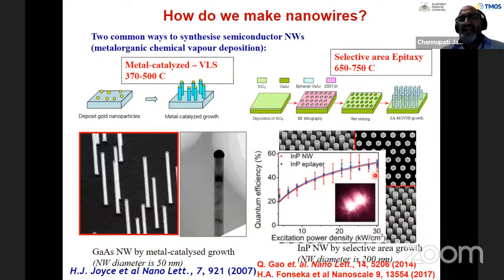So we've taken these indium phosphide nanowires and looked at the light emission from these structures by exciting them with a laser pulse, essentially photoluminescence characterization, where we measure the quantum efficiency as a function of the excitation power. You can see that you can get up to 50% quantum efficiency in these nanowires. And we compared the performance of these nanowires with the epitaxial layers, which are grown under optimal conditions, the blue curve here. They are very much comparable, indicating that in the case of indium phosphide, surface non-radiative recombination is not significant because it's got the lowest surface recombination velocity of any of the semiconductors which I know of. So these nanowires are very good for making lasers and solar cells and other things, which I will come back to.